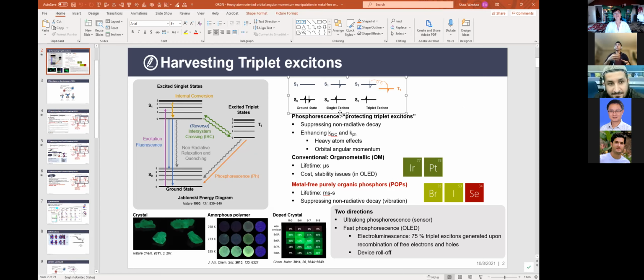Now if we have efficient spin-orbit coupling, we can flip this electron so that it will stay parallel, forming the triplet exciton. I think there should be an animation right here which is actually showing the anti-parallel fashion, but I mean the parallel fashion. If it's parallel, we call that state the triplet state. Because of the nature of this spin flip, this takes time. So when the triplet exciton emits light, it will generate phosphorescence, which has a very long lifetime.